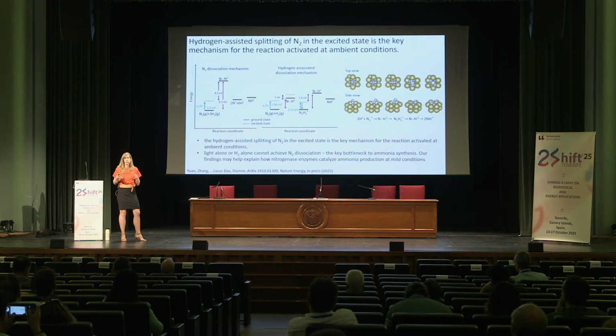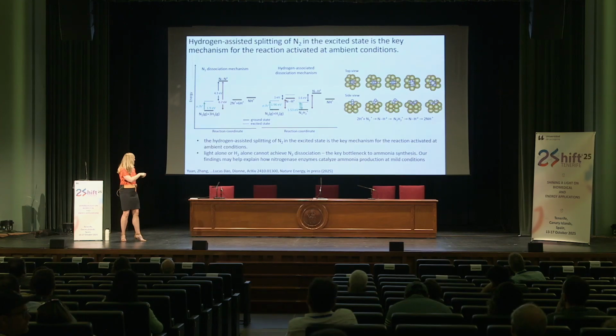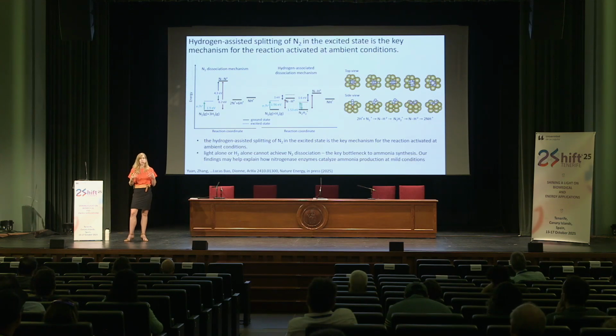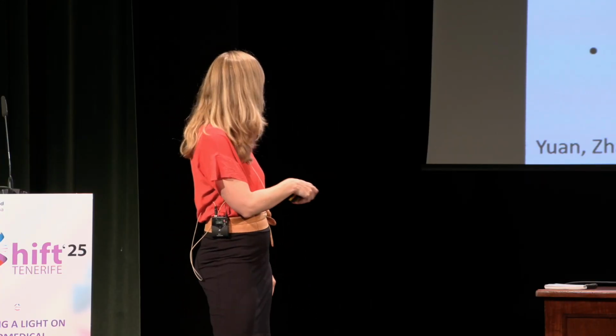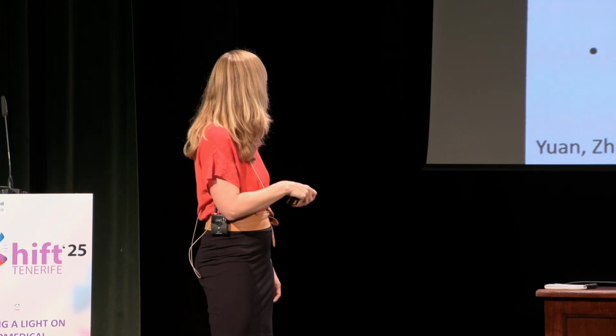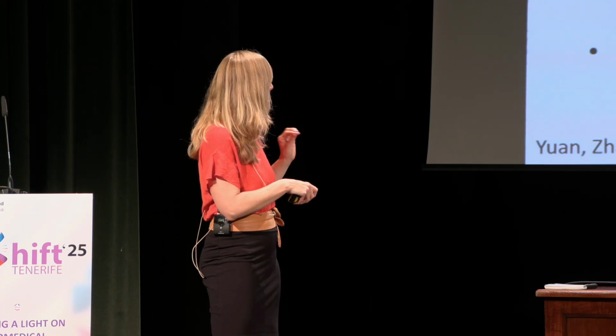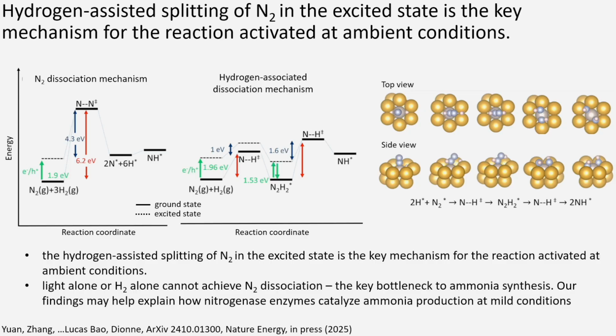So we're actually changing the reaction pathway, and by illuminating at visible frequencies where we have over 1 electron volt, we can overcome the barrier to go from this excited state to this intermediate. So we're using light to drive the hydrogen-assisted dissociation of nitrogen. What this means is that it is this hydrogen-assisted splitting of nitrogen in the excited state that's the key mechanism for how we're getting this ammonia synthesis at room temperature and room pressure.